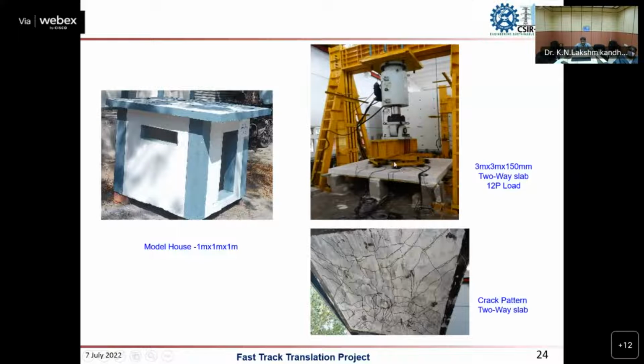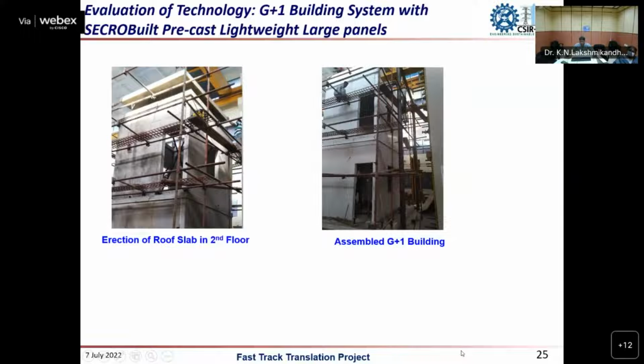And there is no punching shear, because we were loading at 12 points, so no point is crushed or punched. That shows the panel integrity is ensured for the load carrying capacity. And this is a typical view of a G+1 building we developed using this SECROBuilt technology. We tested this for lateral seismic load, and we found this is well suited for any of the worst seismic conditions.